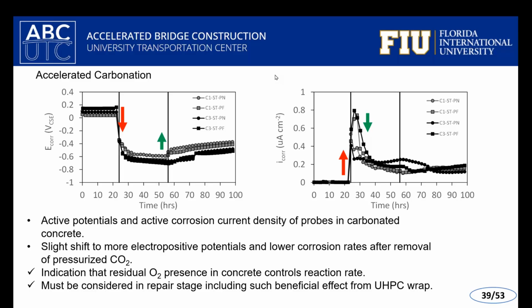So I'll remind the audience that the interior concrete was a low quality concrete. The compressive strength was about, what was it, 3,400 psi or so. And it seems like some of the residual oxygen that was displaced by the CO2 gas outside was able to move back in, or diffuse back into the local area.